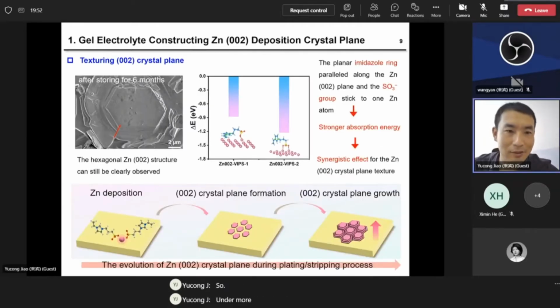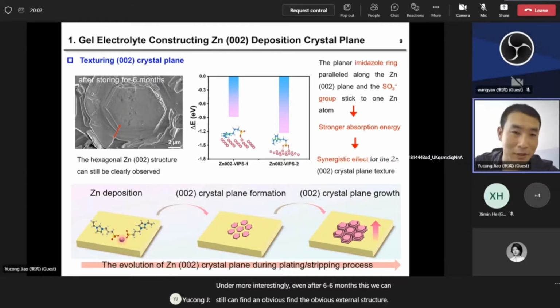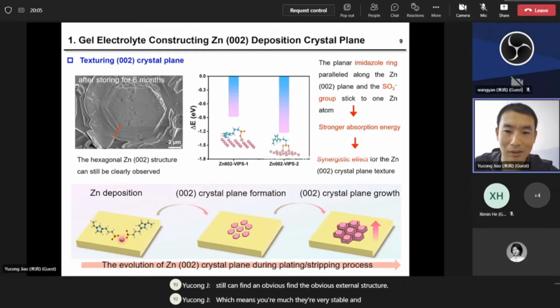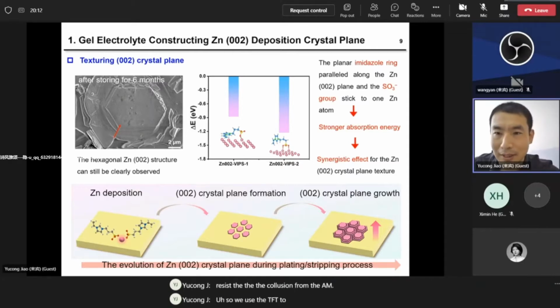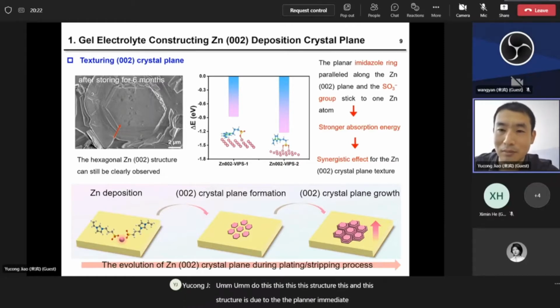More interestingly, even after six months, we can still find the obvious hexagonal structure, which means they are very stable and they can resist the corrosion from the air. So we use DFT to demonstrate that this structure is due to the planar imidazole ring and due to the synergistic effect of the imidazole ring and